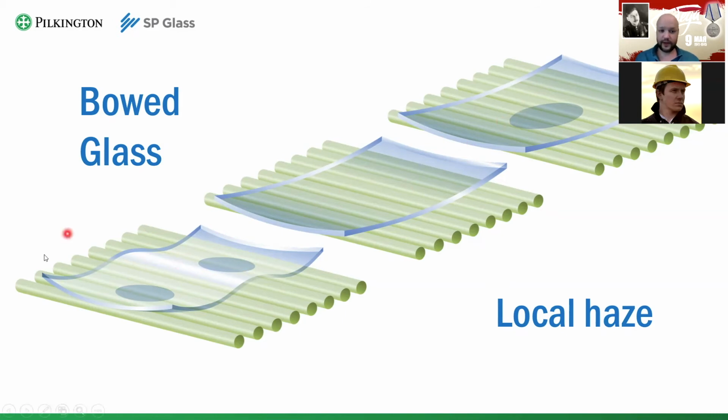Now, this on the left is a kind of an extreme one. If the glass bends too much in the heating, that means there is some problem, either with the furnace or with the operator. I'm not talking about the bending in the end, I mean the final product. The final product can be absolutely flat. But I'm talking about how the glass moves in the heating section.